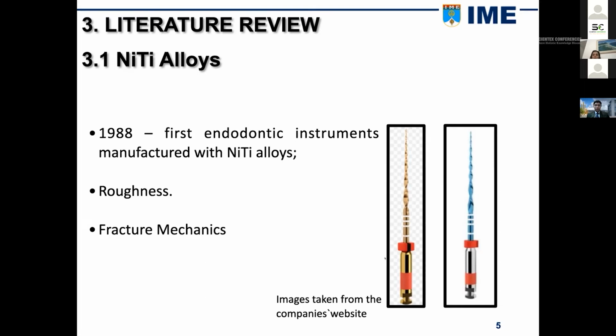Roughness. Several studies have demonstrated that the presence of grooves on the metal surface may decrease the number of cycles to fatigue fracture of endodontic files. Furthermore, some studies have shown that these surface grooves on endodontic files may act as stress concentration points, decreasing their life to fatigue fracture. Cracks commonly initiate in the valleys of the surface grooves. This is followed by nucleation, growth, and propagation.